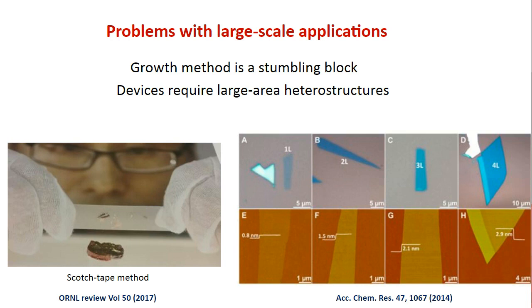And then you individually look into all these flakes that you gather, and you make sure that you have the thinnest layer. Then you go to an AFM and measure the thickness. If the thickness comes out to be roughly, like I was saying, 0.7, 0.8 nanometers, then you got a single layer. If you got a 1.4, you got double layers. So that's how the layers were found out to be either a single, a bi, a 3-layer, or a 4-layer. Now that does not sound to me very productive if you want to do large-scale applications.